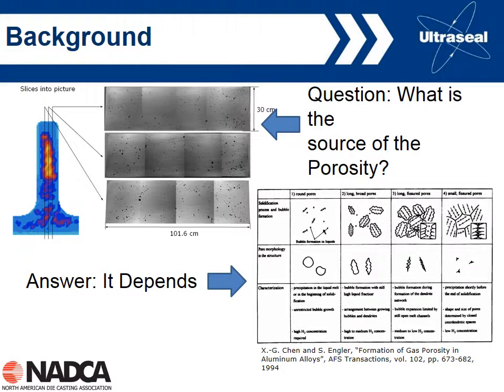And so again, we talked a little bit about this. On the top left here, we've got a schematic, a model of a casting. If we split it up and cut it and polish it, we can see the mostly spherical pores here. And so the question is, what's the source of this porosity? It's smooth, so it must be gas porosity, right? Well, no. The answer, as we talked about last week, is it depends. In the bottom right, we have this drawing that we talked about in detail last week. And what this is looking at is a paper from the 1994 American Foundry Society transactions, when it's talking about the effect of hydrogen concentration on the shape of the pore that will form during solidification. So in this case, all these pores are forming from gas, from dissolved hydrogen.